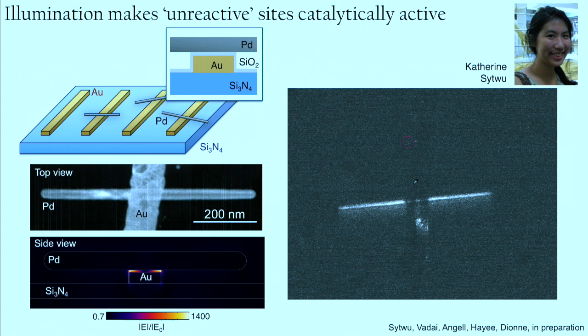And you can see from the side view calculations of the local electromagnetic field that it's strongly enhanced in the gap between the gold nanobar and the palladium nanorod. Now, you could imagine this would just be an entire gold film, except that it would make the movie a little bit less exciting. So these palladium nanorods always hydrogenate and dehydrogenate from the tips. So you can imagine that leaves a lot of the catalyst area unused.